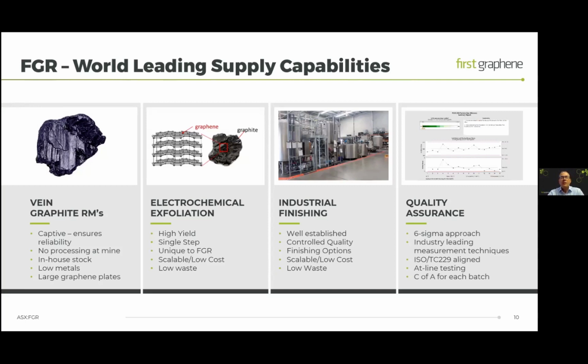The big advantage with the electrochemical exfoliation over mechanical methods is that the graphene platelets are lifted from the graphite raw material by driving ions into the material. It lifts off very large, very thin platelets. So our PureGraph products have a very high aspect ratio, which is the lateral size divided by the thickness, which means they're very high performing products.